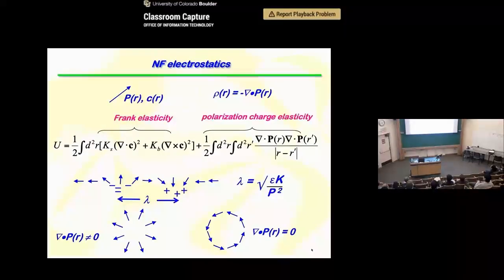All right, so now we'll turn to some phenomenology. So the main physical difference between the ferroelectric nematic and the nematic is the addition of the electrostatic space charge interactions. So if you have a divergence of the polarization, you have space charge. And then the space charge interact by this long-range Coulomb potential. Okay, so you can see the effects of this if you just consider a one-dimensional reorientation in the director field. So this angle is a function of z, and this fills three-dimensional space with basically sheets of polarization in the same orientation.